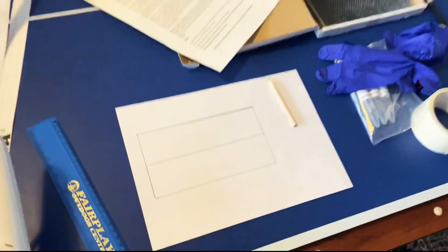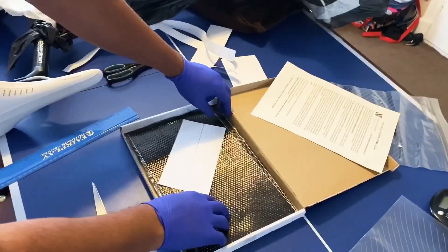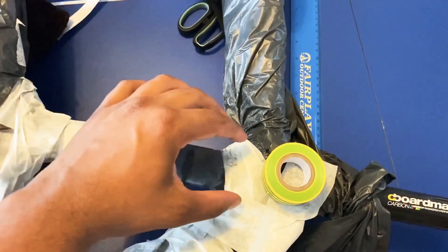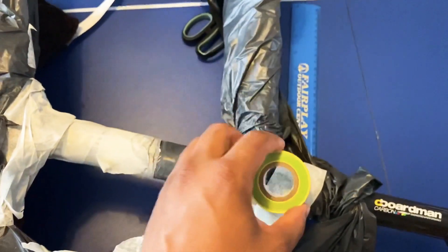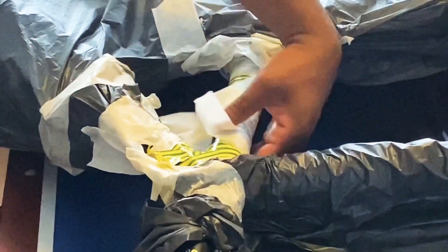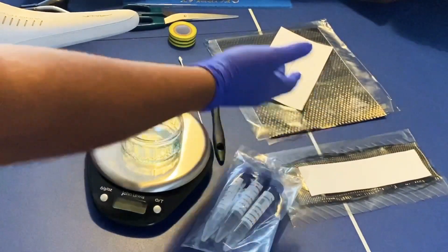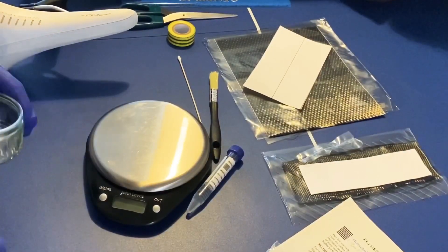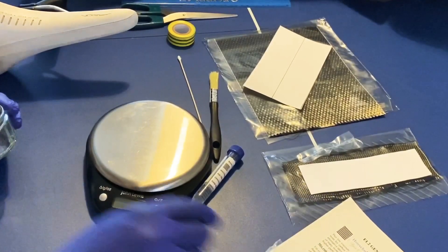This is my final template — I've got it sitting at roughly a 90-degree angle and this is what we need to cut out. I'm taking off the masking tape from around the work area and switching to electrical tape, which should be easier to peel off afterwards, then giving it a final clean with an alcohol wipe. The fibers are ready and prepped, the bike is ready and prepped — now it's time to mix up our epoxy resin with the hardener: 30 grams of epoxy resin with 9 grams of hardener.